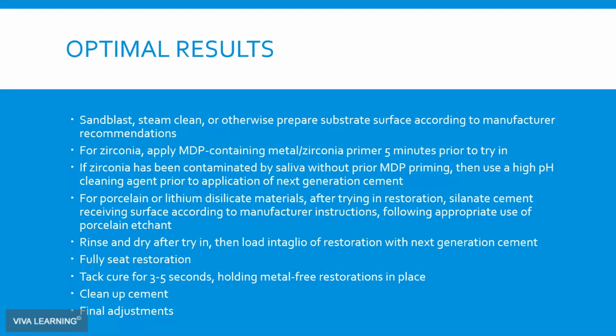Now it's been exposed to saliva, but I already have MDP protecting my zirconia surface. Remember that phosphate group, that functionally active portion of that monomer, that's the part that will stick to the zirconia. And the reason why saliva, we want to prevent that, or you can't prevent it, but you're going to clean up because of those same or similar phosphate groups. So if it's already occupied by MDP, well, there's no room for saliva to occupy those same spots. So I like to put it on first. That way, after I do a try-in, I just wash and dry my crown and proceed with placing the cement in place.